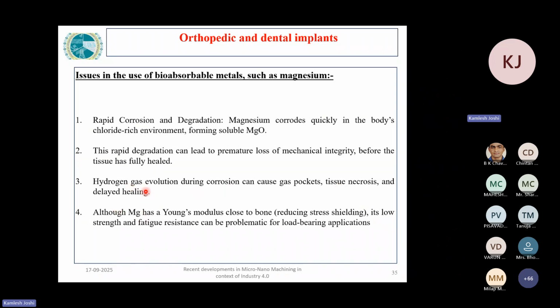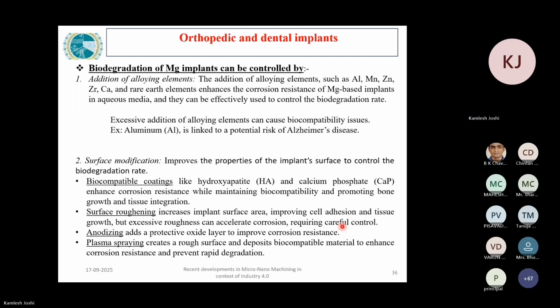So this hydrogen gas evolution is another problem, and it has low strength and fatigue resistance, which can be problematic for load bearing applications. If the application is of static type of loading, then there is no problem. But if the application is of dynamic nature, then due to its lower fatigue resistance, it may cause some problems.